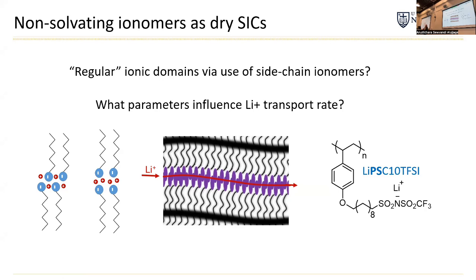Because of course, there are many inorganic materials that have very, very high lithium ion conductivity. So we're trying to understand, can we engineer that into a plastic type material? I just showed a structure of one of the polymers we've been looking at. So far, we found that these systems still have very low conductivity, so they're not competitive, but we're really trying to focus on the mechanism and understanding how the lithium pops, or what we can do to get it to pop in these types of plastics.